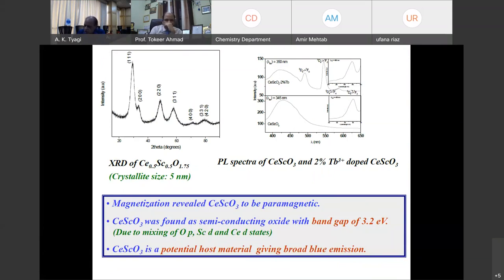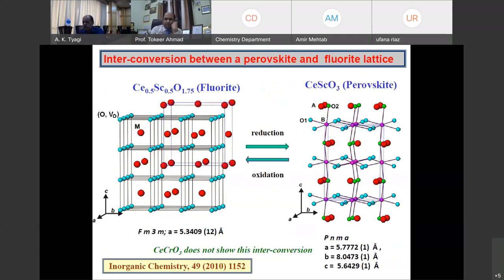However, the most important result of this work is shown in this slide. We made by combustion method Ce0.5Sc0.5O1.75. Reduce, you get CeScO3. Oxidize, you get fluorite. So this couple of structures you can interconvert n number of times. Remember, 5 minutes back I showed you one more compound, CeCrO3. Surprisingly, CeCrO3 does not show this interconversion. CeCrO3 adopts this structure, and once you oxidize, it shows phase separation to CeO2 and Cr2O3.